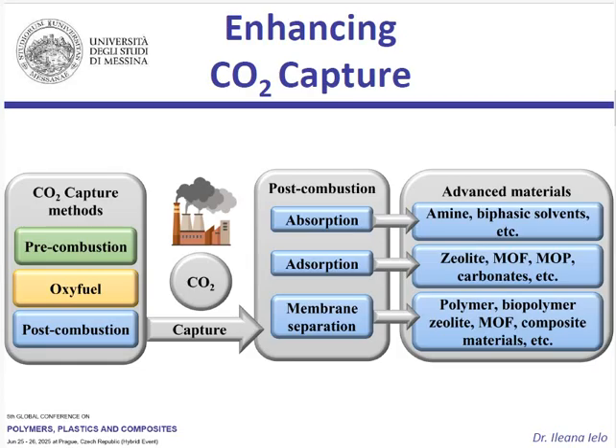While materials like biochar and carbonized biomass offer cost-effective options, advanced carbon nanoallotropes such as fullerene, carbon nanotube, and graphene provide superior surface area and enhanced surface chemistry for CO2 capture. For materials like MOFs, CO2 capture is further improved by polar functionalization of the pore surface, for instance by grafting OH or NH2 moieties, which allow for tailored CO2 molecule hosting. By focusing on material innovation, we can significantly boost the efficiency and feasibility of CO2 capture technologies.